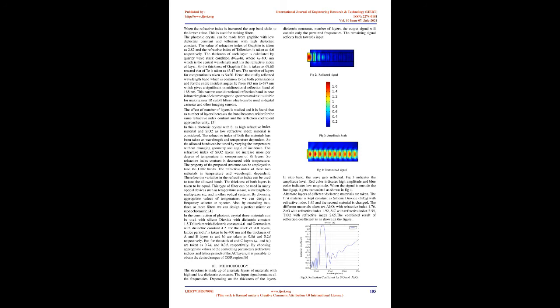Literature survey. The omnidirectional reflection characteristics of a one-dimensional photonic crystal with the first material as silicon dioxide with refractive index 1.5 and the second material as germanium with refractive index 4. The thickness is taken as 600 nm and 400 nm respectively with the number of layers as 10. It is clear that the common range of unit reflectance is from 2247 nm to 2438 nm, so that the total omnidirectional reflection range has a bandwidth of 191 nm.